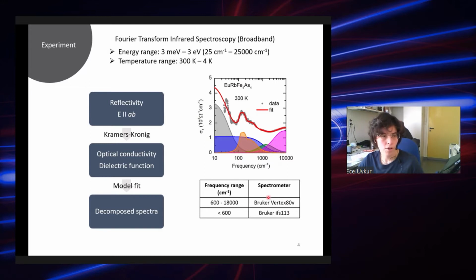This is just additional information: we performed the measurements in 3 different setups. For the infrared part, we used 2. That's why we had some empty spots between two different measurement setups, but this is not really important for the discussion of superconductivity and the superconducting gap. Once you have this reflectivity, which we measured in plane, as iron pnictides tend to be quite thin, you can do some Kramers-Kronig analysis on it, and then you can obtain the other optical variables like the optical conductivity, as I showed here, or the dielectric function as a function of frequency. Once you have this, you can use model fits, where one can see a couple of Drude components, some Lorentzians and interband transitions, and one can decompose the spectra using these model fits.